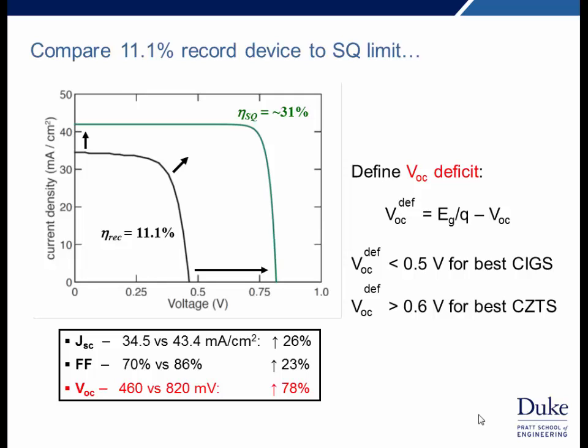And as a metric, one can define an open circuit voltage deficit, which is just the difference between the band gap and the open circuit voltage. For high performance CIGS devices, this value is below 0.5. Best devices are around 0.4. For all of our CZTS devices, and we've looked at many thousands, the value is greater than 0.6, often greater than 0.7. So this is clearly something that needs to be addressed.